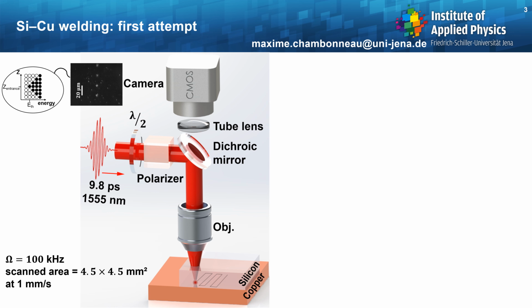To do so, we will illustrate semiconductor metal ultrafast laser welding with silicon and copper. We will also employ the following arrangement. It relies basically on 9.8 picosecond laser pulses at 1.55 micron wavelength. One can note that at this wavelength, silicon is highly transparent, meaning that we can reach the interface between the two materials. Then, the input pulse energy is controlled by means of a half-wave plate and a polarizer before the beam is focused to the samples by an objective lens.